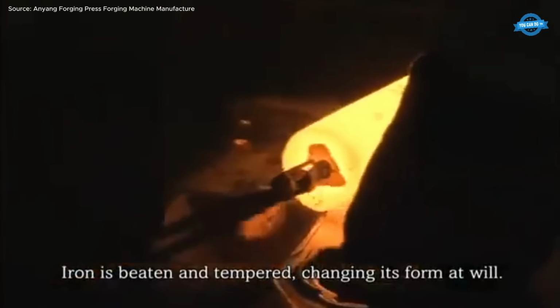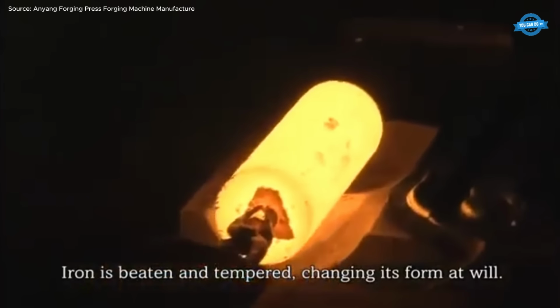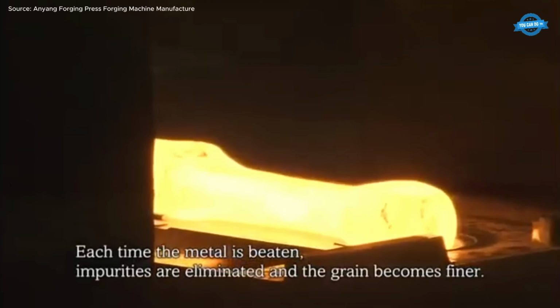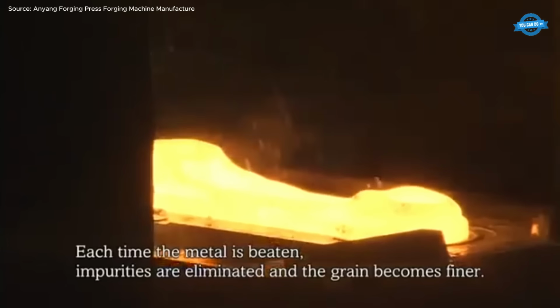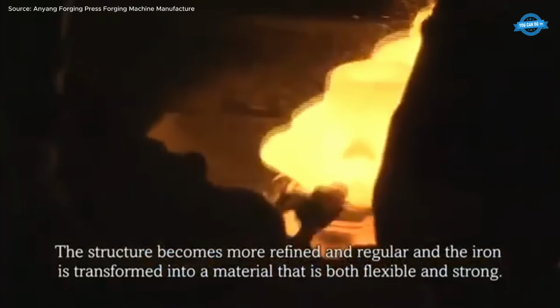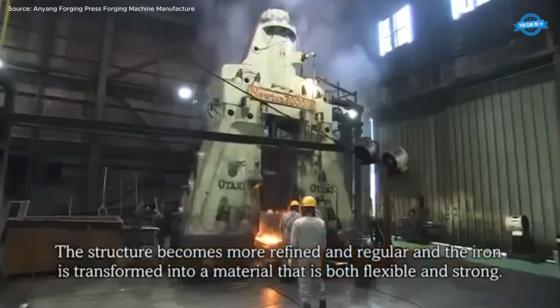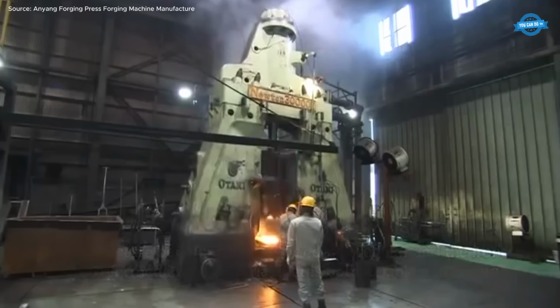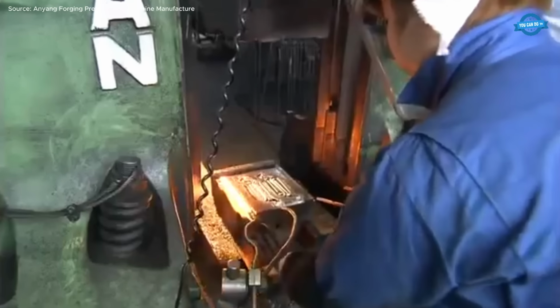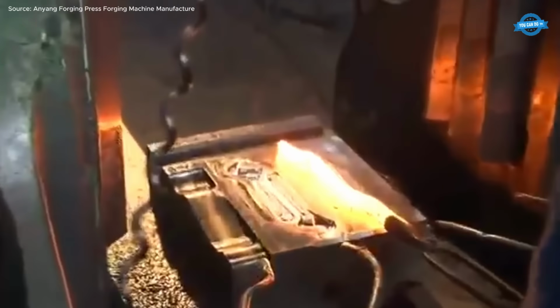White-hot steel glows beneath the hammer, its structure transforming with every controlled strike. Closed die forging technology harnesses this intense force to reshape heated metal inside precision machine dies, producing components of exceptional strength, toughness, and dimensional accuracy. Each impact refines the grain structure, eliminates internal voids, and aligns the metal flow along the geometry of the part. The result is a dense, homogeneous microstructure engineered to withstand extreme mechanical stress.